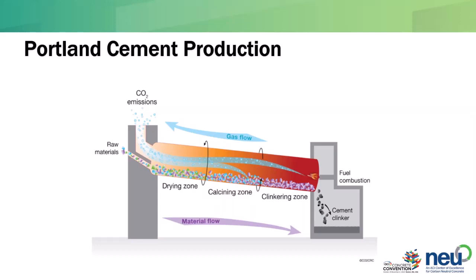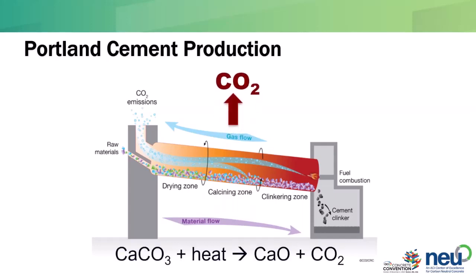Anyway, so typical cement kiln, right? And we have raw materials coming in on the left, namely limestone or some form of calcium carbonate, shale, clay, various other materials. Now the kiln is at an angle, rotates real slow, and there's a huge flame at the bottom, right? So as the materials go through, they start to heat up. You lose the water, eventually the limestone hits a certain temperature, and you start to lose the CO2 from the limestone, right? So that's just a natural chemical reaction that happens when you heat limestone, but it contributes a significant amount to the total carbon footprint.